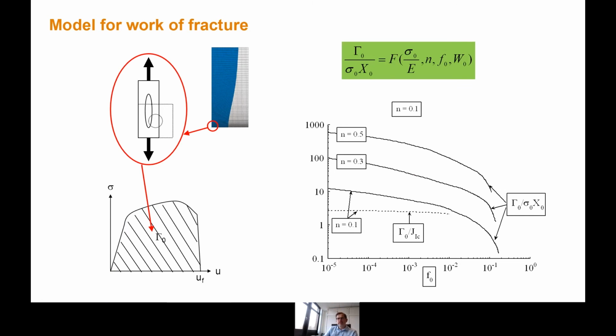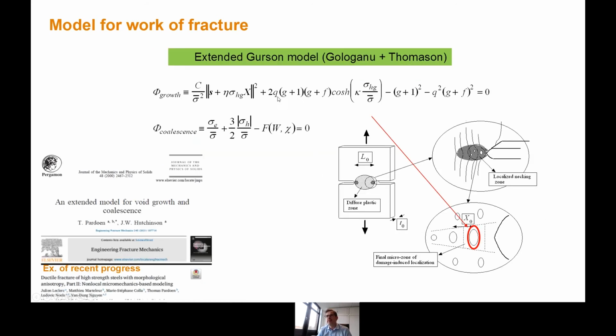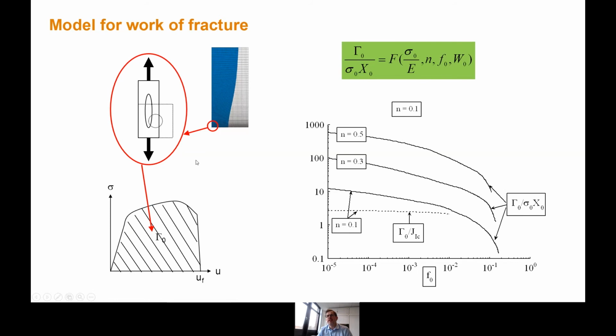So what I did at that time, I was working on damage. This is my old subject. This is the subject of my heart. And I was using this complicated Gurson model with another coalescence model, whatever the details, to estimate the work per unit area needed to break a material element that would be located in the middle of the neck at the tip of the crack in the panel. So I was applying a stress triaxiality corresponding exactly to the loading condition of a material point there, to estimate the evolution of stress with displacement and calculate the gamma zero.